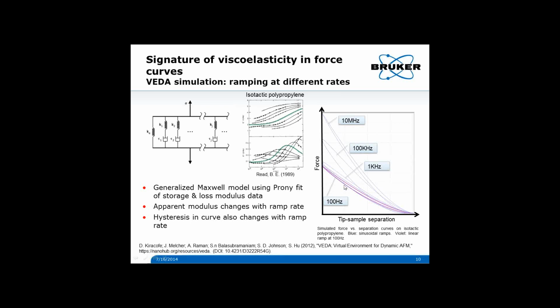And basically, you see right away that there's two things that are happening with these force curves as we increase the ramp rate. For one thing, these are getting steeper, so the apparent modulus is increasing. If we were to calculate the modulus for each of these curves, we would see that it was increasing, even though it's the same material.